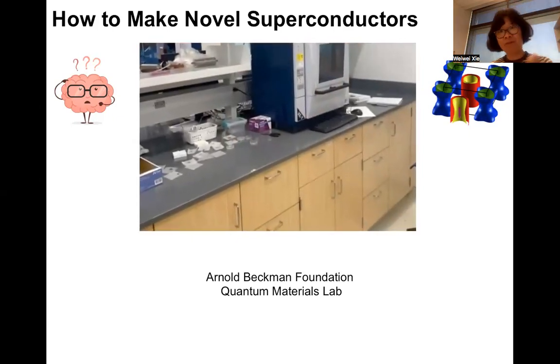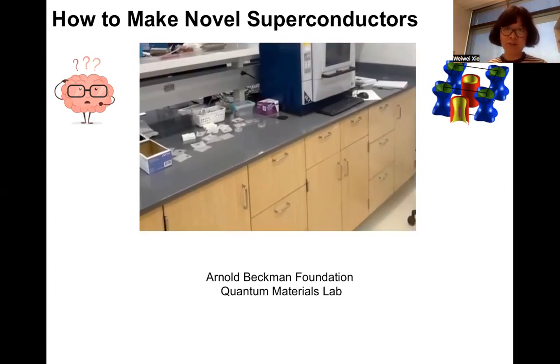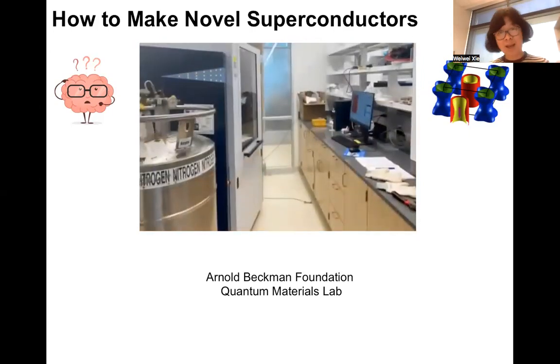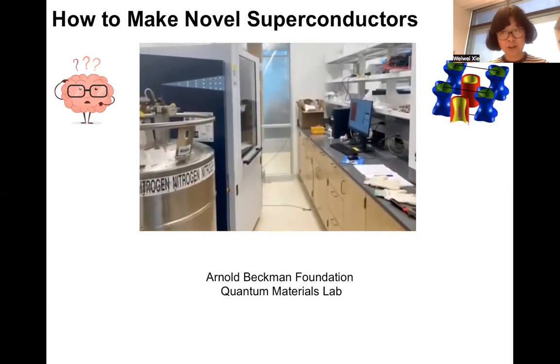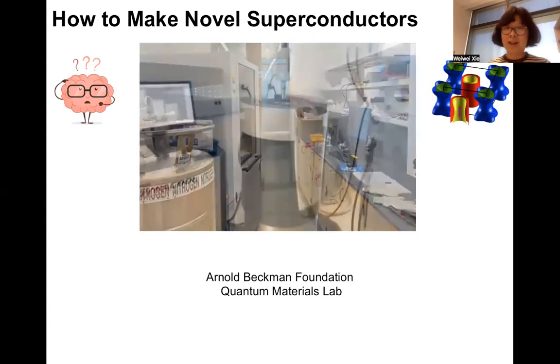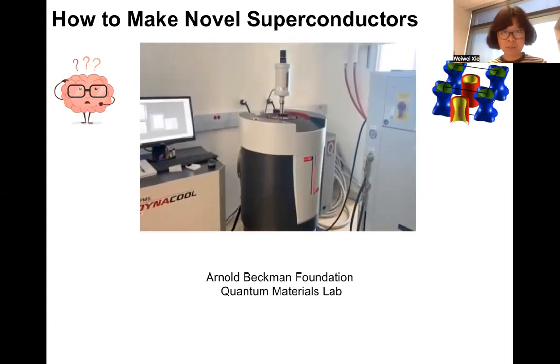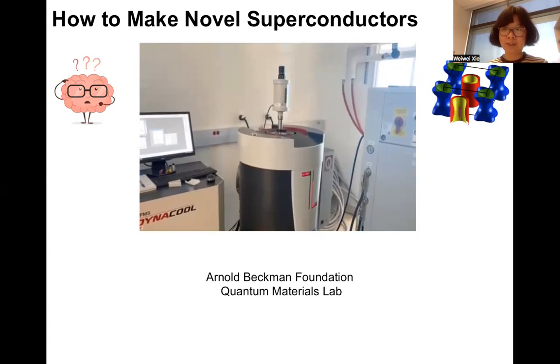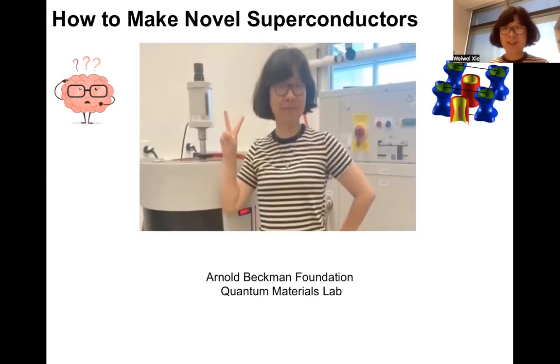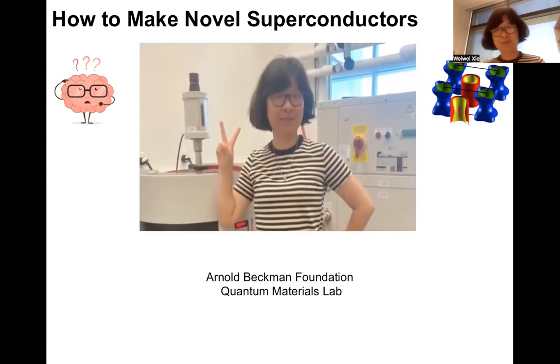Then we perform powder X-ray diffraction to find the phase, as well as single crystal diffraction to determine the crystal structure. After that, we measure the superconducting properties. The whole system here is funded by the Beckman Foundation, and then we can make the new superconductors.